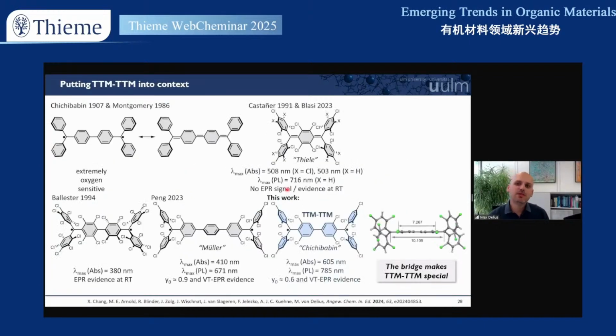So here we really lean on these literature comparisons. I guess one thing we explored ourselves, and here the credit goes to my colleague Alexander Kühne and his student Julia Zolk. So they calculated our molecule, or molecules now, I should say, with TD-DFT calculation. So we do understand why this bridge is so special. We do understand even the transition states, so we did not just calculate HOMO and LUMO, but the S0, S1, and the triplet states. So we do understand this very well.